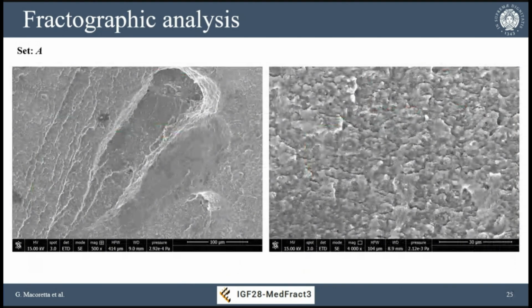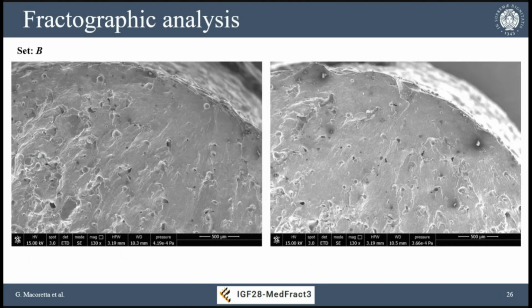Looking in detail at fatigue crack propagation, we see the material has no significant delamination, no melt-pool delamination, but in some cases we have jumps between different planes due to some delamination around molten pool geometries. This seldom occurs, but sometimes the melt pool boundaries can become weak points, only in the final or middle part of fatigue crack propagation.